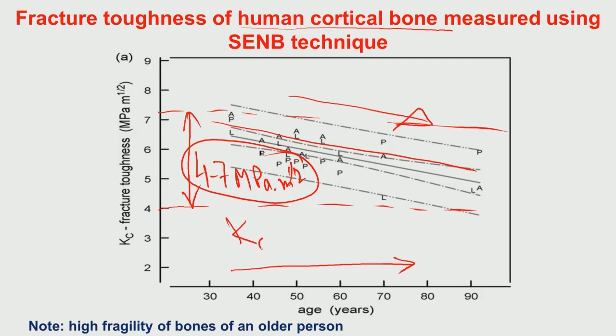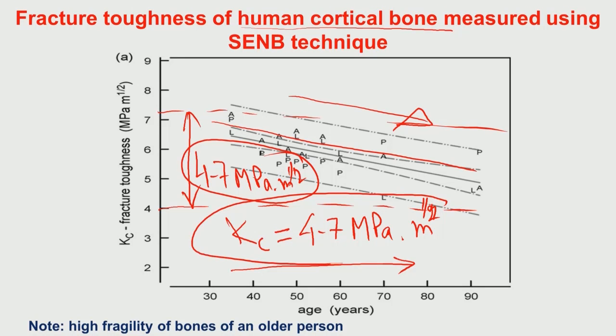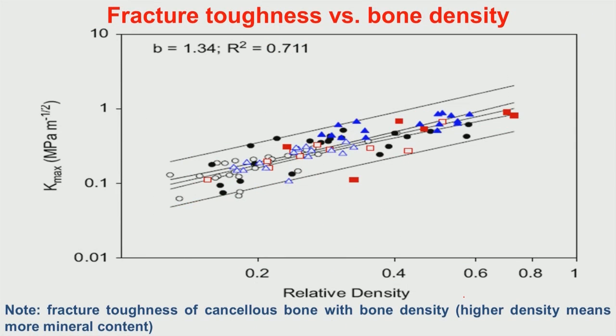So, if any material is to be used as a bone replacement material, its fracture toughness should somehow be within this particular window, 4 to 7 MPa square root meter. Although larger the fracture toughness, better it is. However, 4 to 7 MPa square root meter is the typical cortical bone fracture toughness, and that is what one has to match with that kind of natural bone.